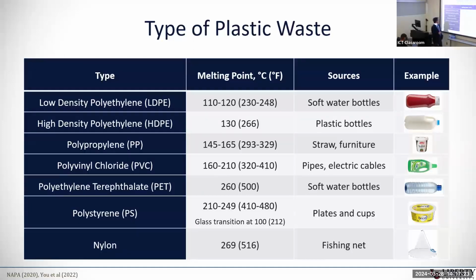So this shows the typical types of plastic waste. There are low density polyethylene, HDPE, PP, PVC, PET, PS, and nylons, with their melting points and sources. We look at the melting temperature because asphalt paving materials are produced around 300 to 350 Fahrenheit. So when we use waste plastic as a wet process, we have to choose the materials that melt at the mixing temperature, but for dry process, we pick the types of plastics that have a higher melting point than the mixing temperature.